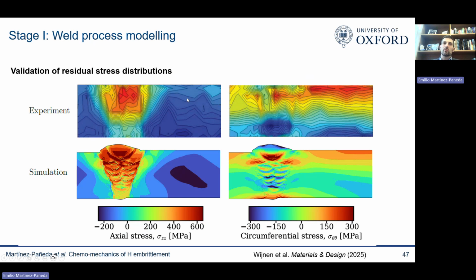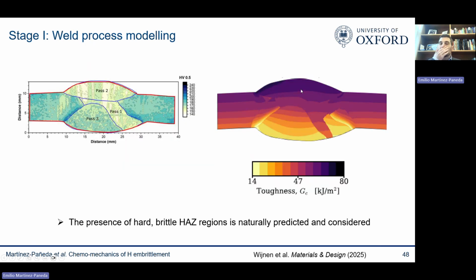And here you see a comparison with residual stresses. It's difficult to measure residual stresses in experiments - you see here, this is with X-ray diffraction. But again, using the same scale as in the hardness maps, we get what I would say is quite a decent agreement.